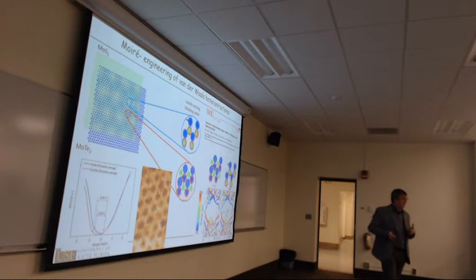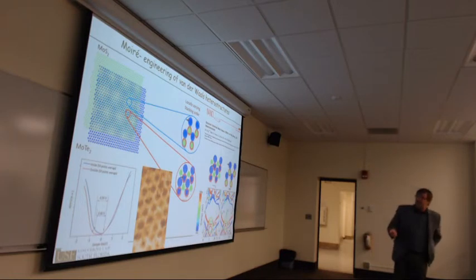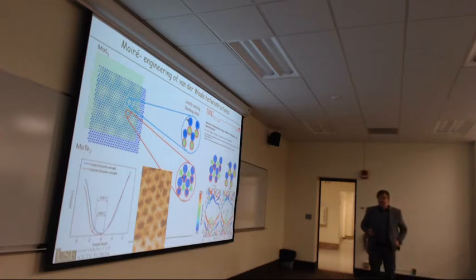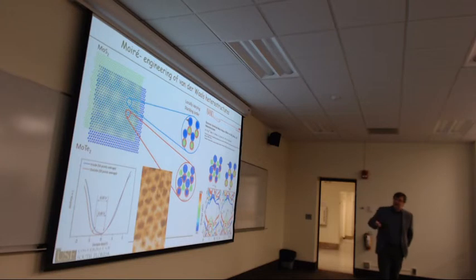It's really electronic in origin, and you can do scanning tunneling spectroscopy at different spots inside and outside, and you see the variation of the band gap in these spots, which is due to the interlayer interaction between the two materials and the spatial variation of the coordination of the atoms on the top and bottom layer in this case.